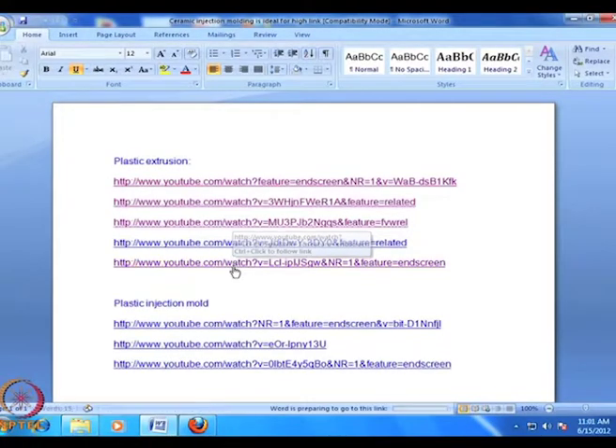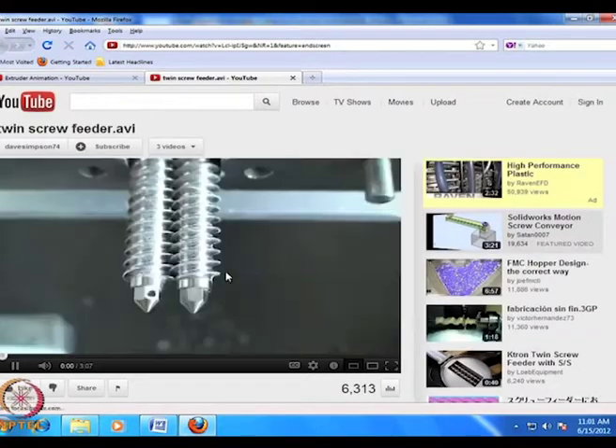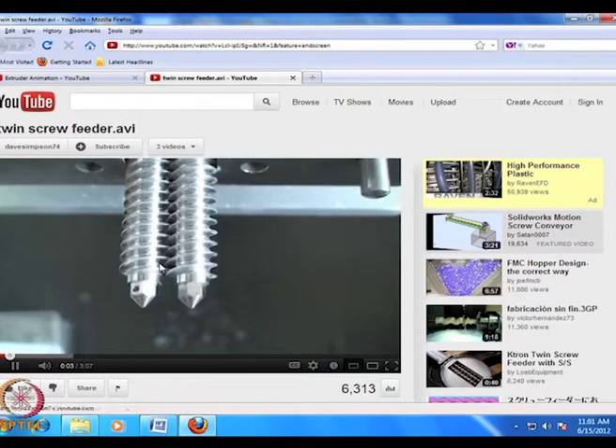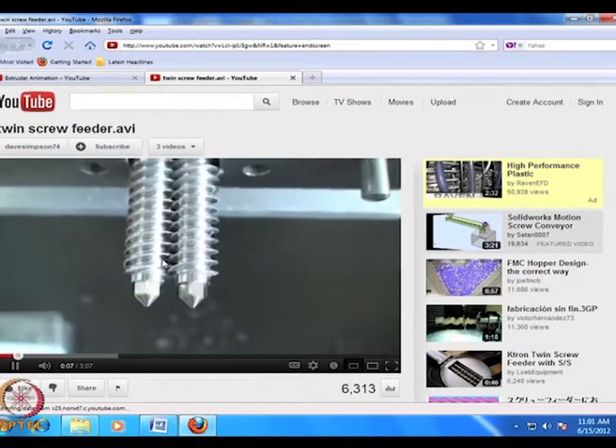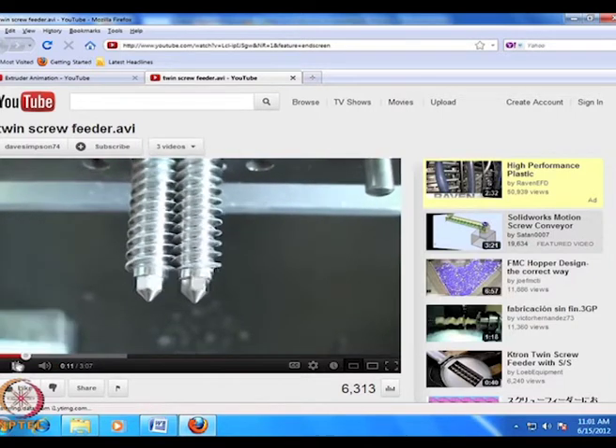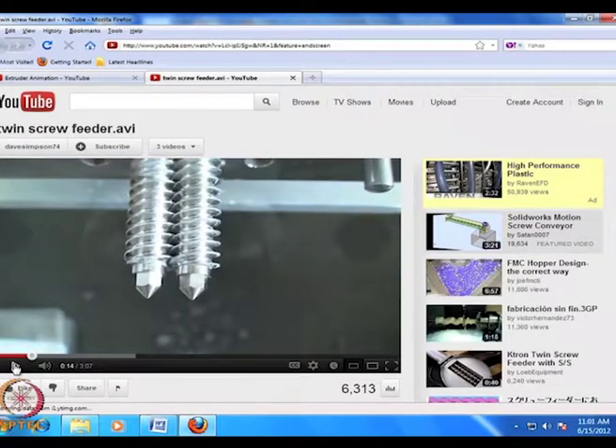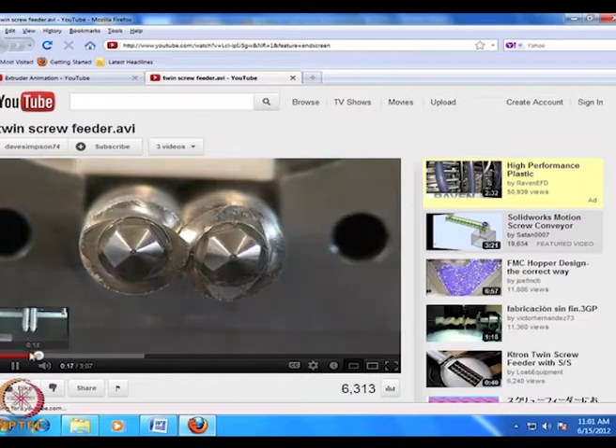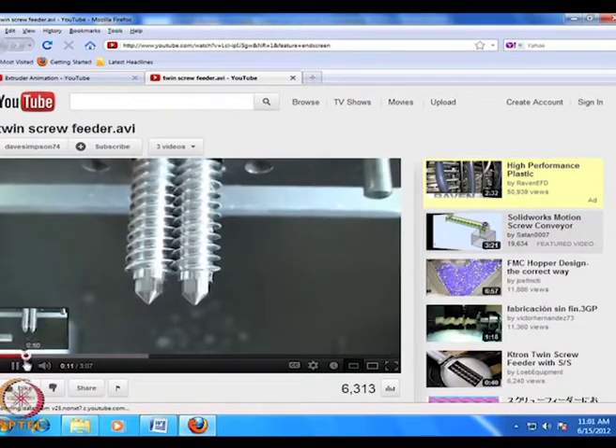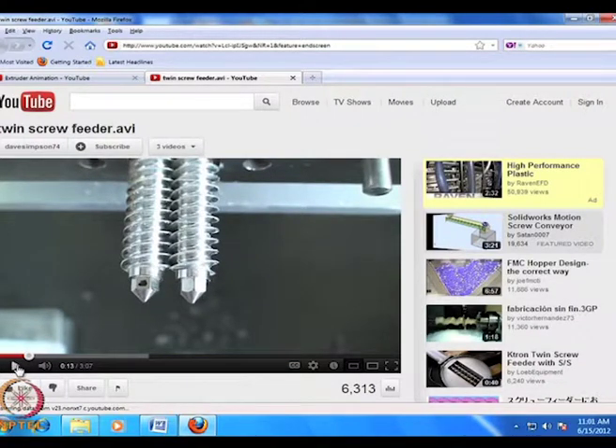I would like to focus a little more on the twin screw feeder. This is a twin screw feeder from above at 14 RPM. You see, this is a twin screw feeder and I have frozen it at a particular point. See how the blades are. This twin screw is rotating in the same direction. Just watch. RPM is set to 14. They are rotating in the same direction.